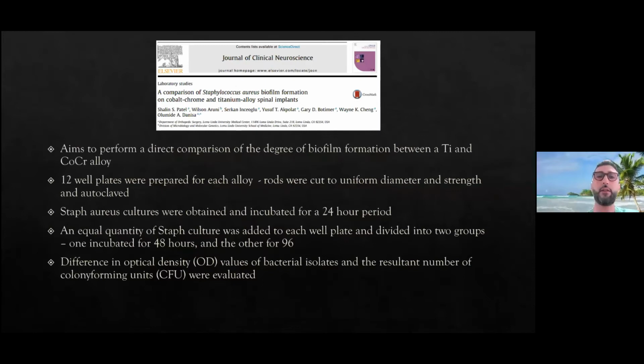And so, I've included a study here from the Journal of Clinical Neuroscience, which compares Staph aureus biofilm on cobalt chrome and titanium alloys. There's also studies looking at stainless steel. I didn't include them because there's just a lot to present here, but it's pretty well established that stainless steel has a higher rate of biofilm formation. In this particular study, they took 12 well plates for each alloy, so 24 total, obviously uniform diameter. They autoclaved them. They then had these Staph aureus cultures, which they incubated, and they added an equal amount to each of the well plates.